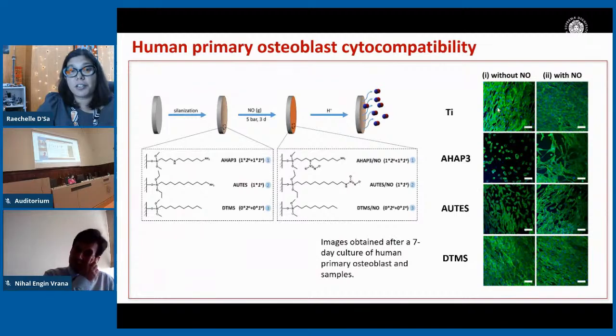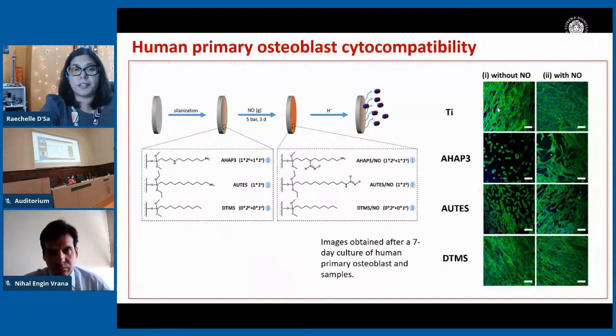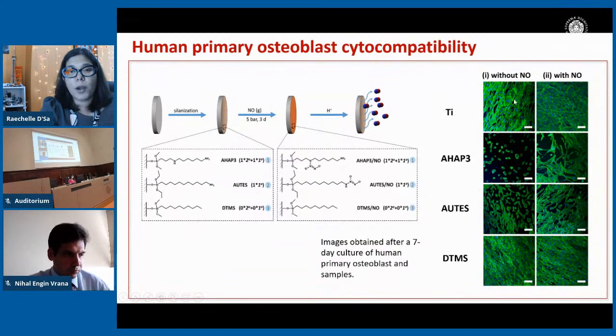Do we still get a positive cellular response on the surfaces? On our titanium samples, the osteoblasts grow quite well with or without the nitric oxide on the surfaces. And on our DTMS surface, likewise, with no ability to form the diazeniumdiolate donor, we see that the cells grow quite well on surfaces that are capable of releasing nitric oxide.